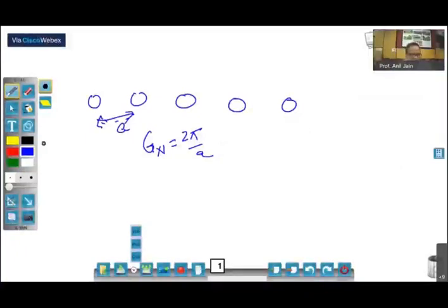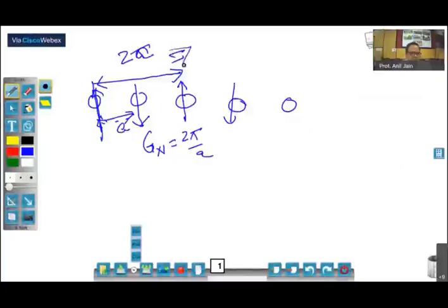However, let us say this hypothetical material is ordered in an antiferromagnetic structure. Now this magnetic ordering is antiferromagnetic. You can clearly see that now the length of the magnetic unit cell is 2a, and this implies that your magnetic reciprocal lattice vectors are pi/a, 3pi/a, something like this.